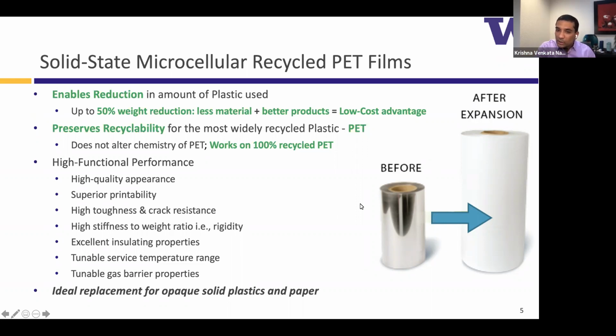So what you're seeing here is the raw material roll extruded going into the process. And what comes out is an opaque, bright white material with twice the area and the same weight. And that whiteness is coming from all the light that is getting reflected back because the bubbles are acting like prisms. It's very hard for us to make anything less than 90% brightness. The paper industry, in order to get to the same brightness, uses a lot of chlorine to bleach the paper to that kind of whiteness, right? So you can see the benefits right there.